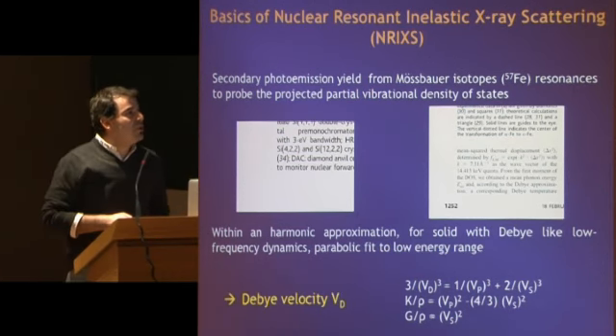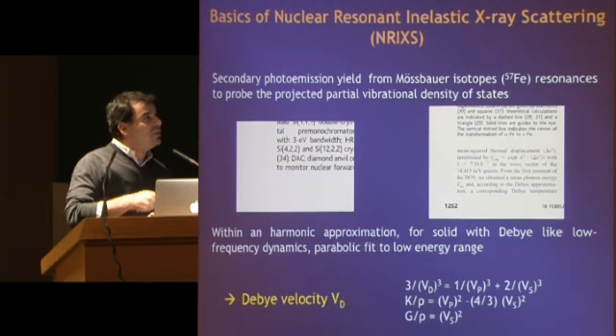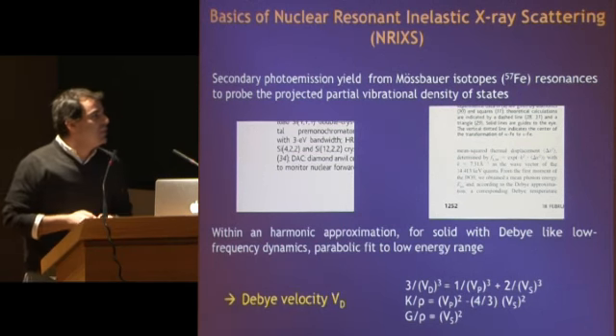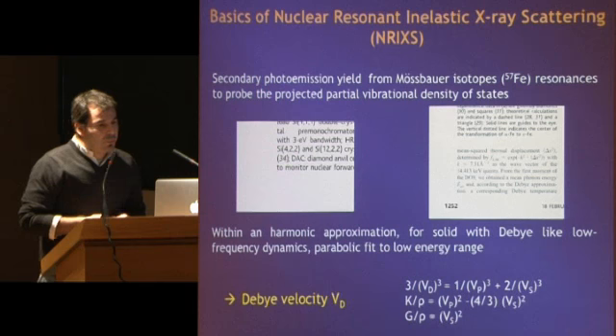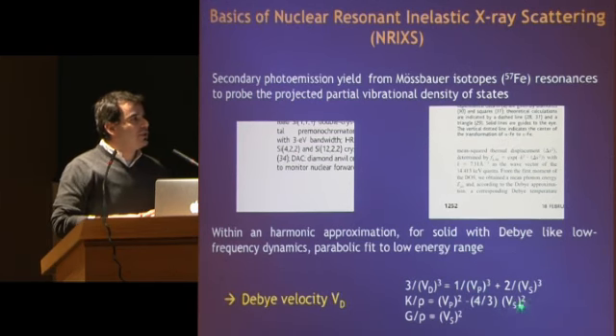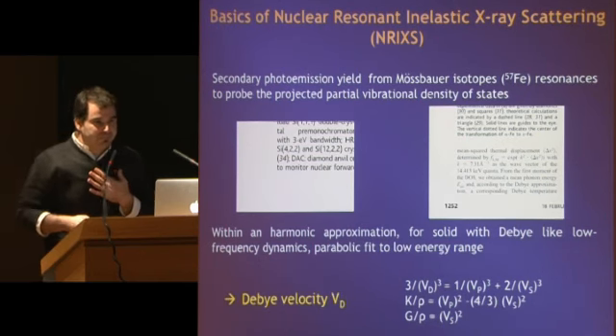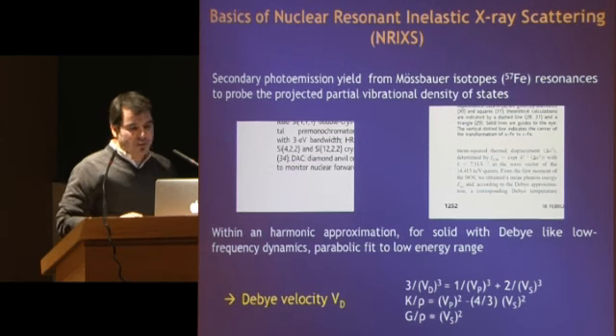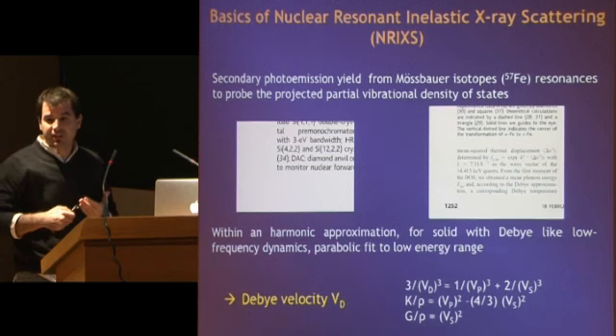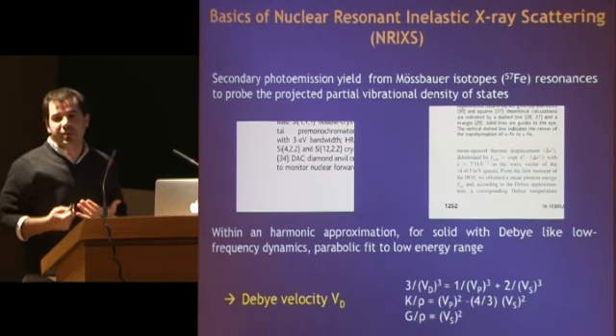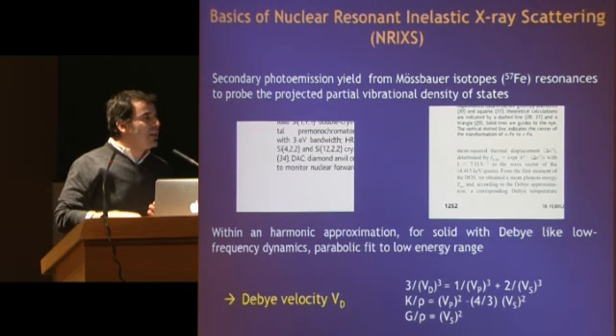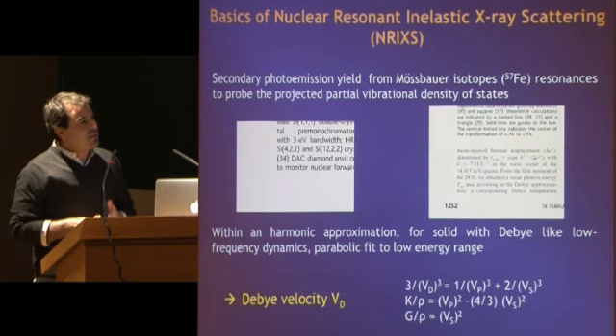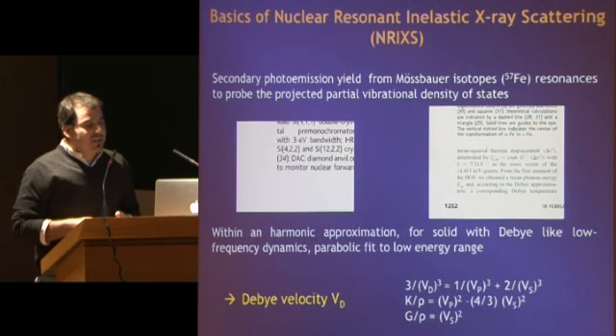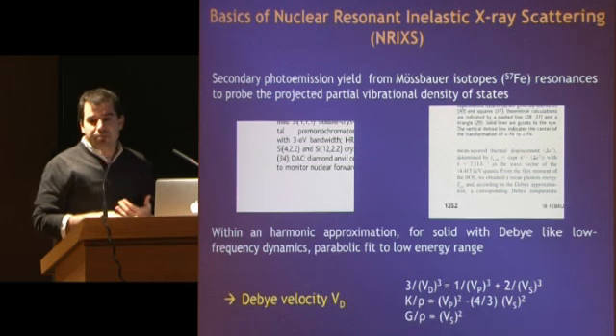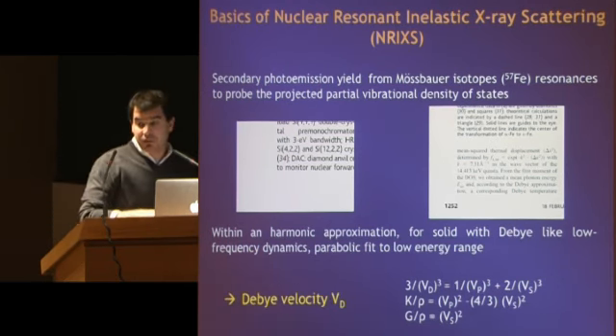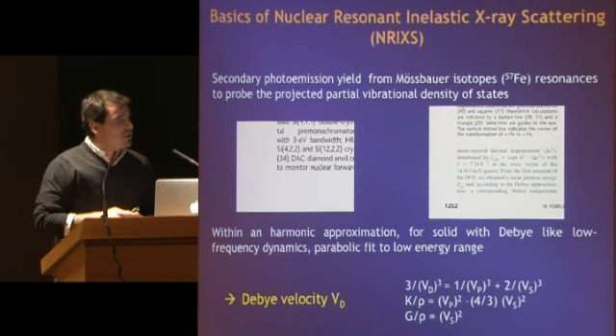And given a series of approximations, from a parabolic fit to the low energy of the phonon dispersion, we can get the mean Debye velocity, which, combined with the equation of state, gives the compressional sound velocity Vp and the shear sound velocity Vs. So, as you can see, this technique involves some degree of approximation. It's rich in information in the sense that from integration of the phonon density of states, many thermodynamic parameters can be derived. But if we just stay with the case of sound velocities, in practice what we can say is that determination of Vs is quite insensitive to the different approximations involved in the use of different equations of state necessary in the technique, while this is not the case for Vp.